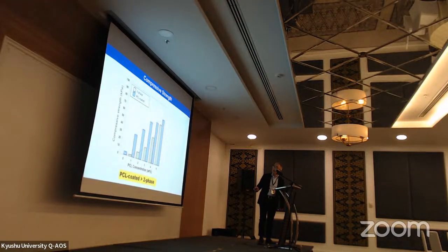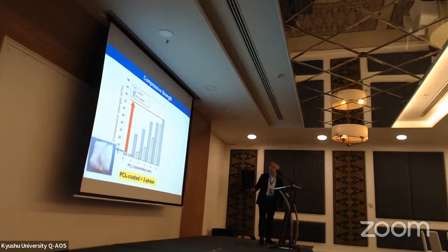Then I compared the mechanical properties. This is compressive strength, and I increased the PCL concentration. The 0% means pure hydroxyapatite structure. You can see great improvement of strength like this, and coating is better than the two-phase structure. Without the polymer phase, we have brittle fracture behavior. However, if we introduce a polymer phase, due to polymer ductile deformation, we can improve the strength, okay?